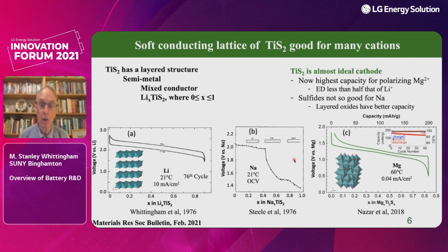Brian Steele was looking at the sodium compound, and again, you can cycle this material, but the sodium compound is disappointing in the sense there's a huge voltage change here. And it looks like today the layered oxides are much more attractive for sodium than the layered sulfides. But what this soft lattice did allow is for divalent cations to be readily and reversibly intercalated. And Linda Nazar's group basically displaced the molybdenum sulfide Chevrel phase as the record holder for magnesium using titanium disulfide.